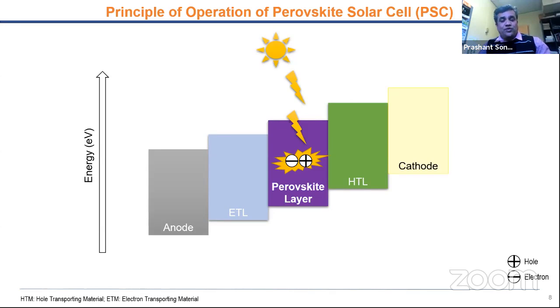The perovskite can absorb or emit light depending on its band gap. Particularly in case of a perovskite solar cell, once you shine a photon on it, exciton formation happens. And one of the beauties of perovskite material compared to the classical organic semiconductors is that in case of organic semiconductor, your exciton cannot travel a really long distance. They might have a 20 nanometer exciton diffusion length. But in case of perovskite layer, exciton can travel up to the micron level.